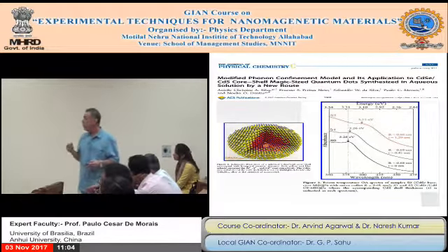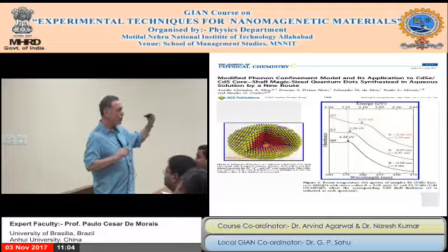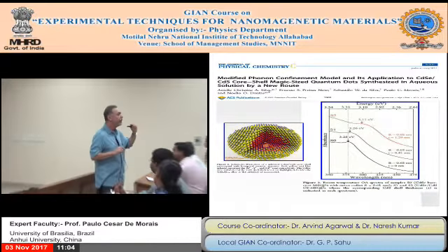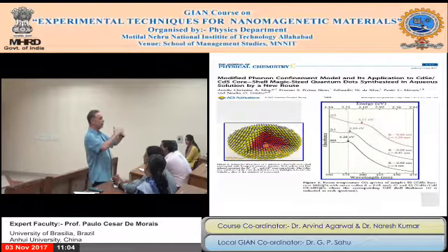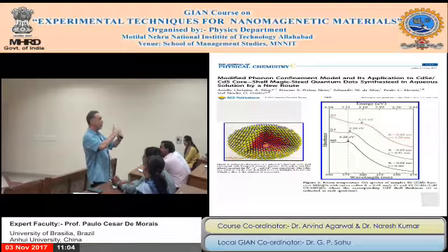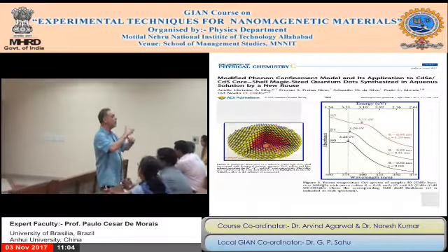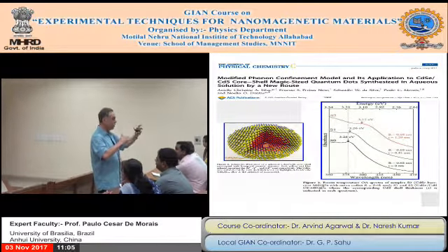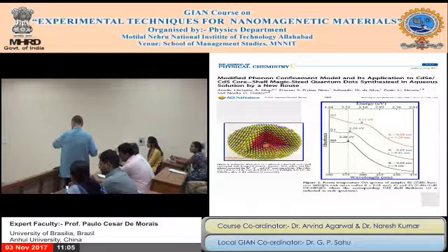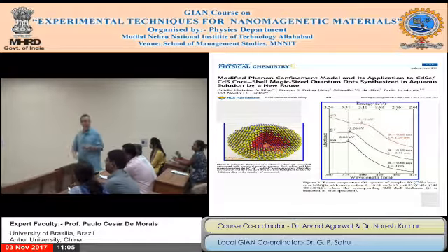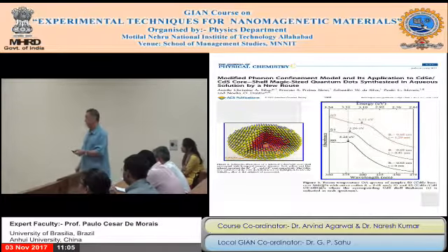In this case, we observe that there is still a layer in between the core and the shell, but this layer now is much thinner. We managed to reduce it, which means the interface between the core and the shell is sharper. So we learned how to modulate this interface. Not only the core and the shell, but also the interface. We could probe all these samples using absorption and photoluminescence. Very important techniques to check this.